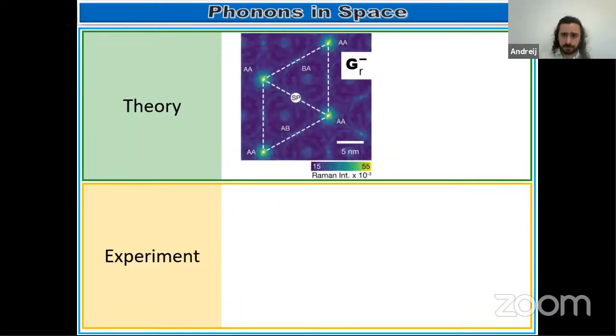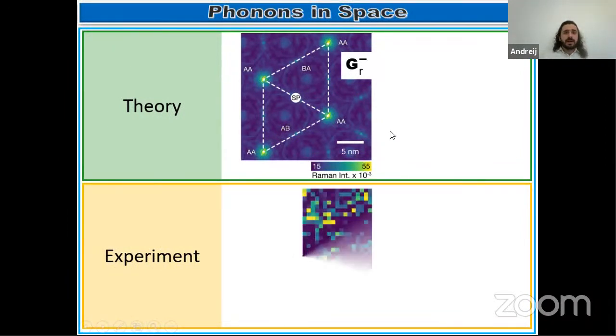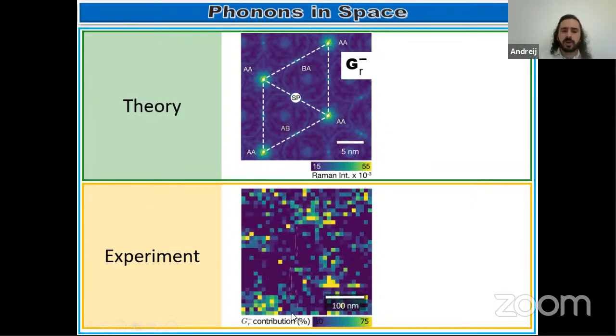Okay, and I now show the phonons in space. So the theory says that the GR minus mode, here they plot the Raman intensity expected for this mode. The intensity varies a lot in space. So they observe larger values at the AA sites, like the experiment. In the experiment, we plot the GR minus peak contribution over the space, and we see large intensities at the AA sites, like the theory observed.